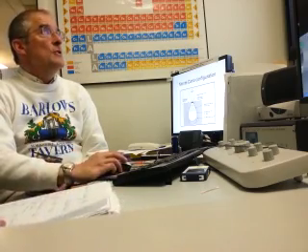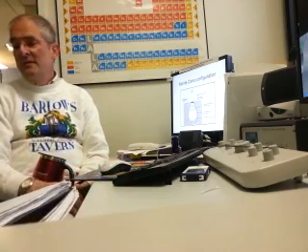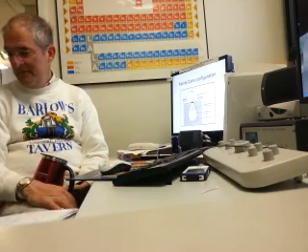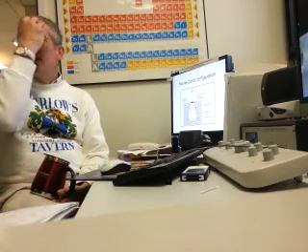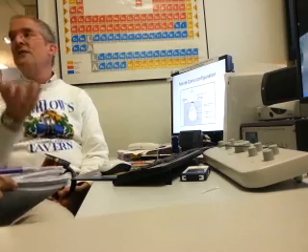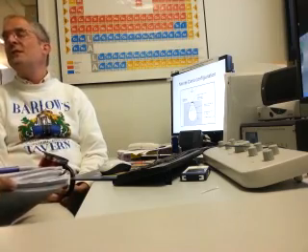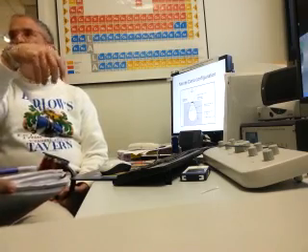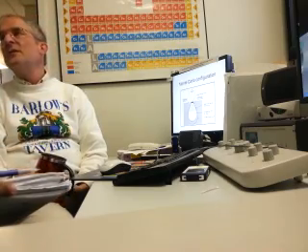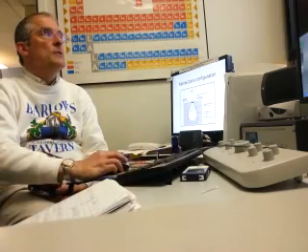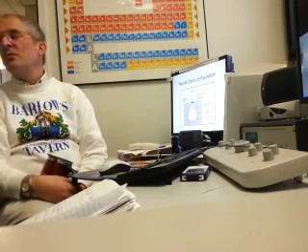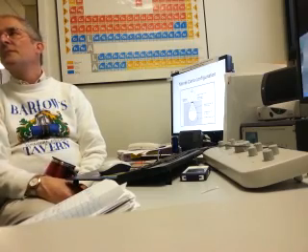So up here, when the collision takes place up near the surface, then there's enough energy in those electrons to exit the sample if they're pointed that way. If they're pointed down, then they'll go down into the sample and they will just be absorbed. And in being absorbed, they would then be part of the flow of electrons through the sample, which you would pick up in your specimen current meter. But not in your secondary? No, because they didn't exit the sample.